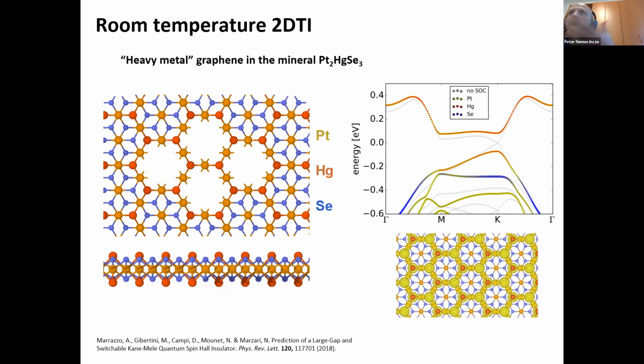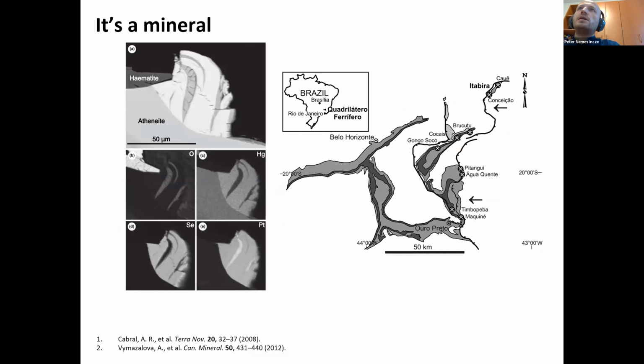If you take out spin-orbit coupling, which you can do in DFT, you can see that it has a band structure very similar to graphene. It shows a Dirac cone. But if you switch on spin-orbit coupling, you get a band gap which is quite large, well above 100 milli-electron volts. Now, the material itself was discovered in 2008, and it is a mineral.